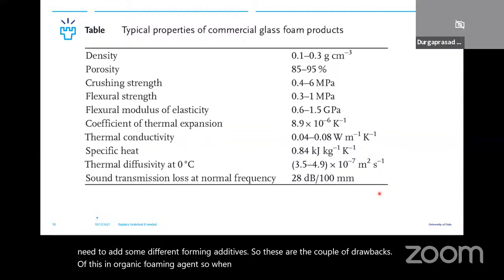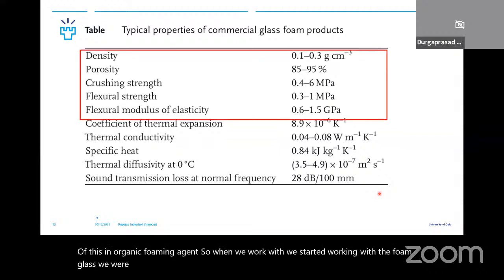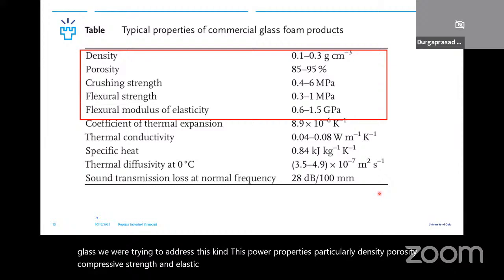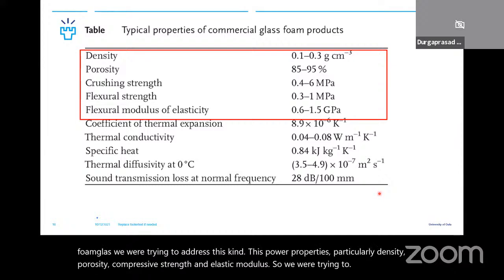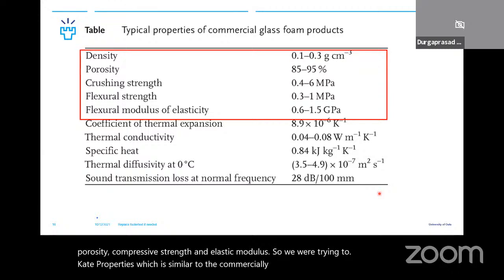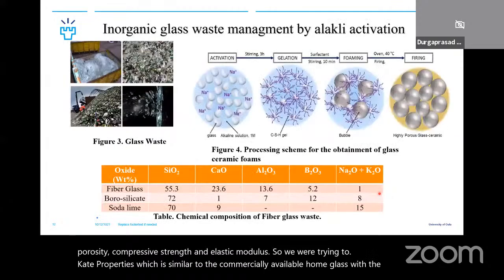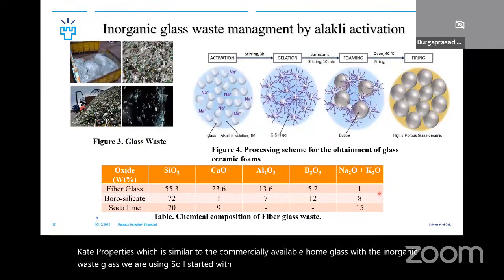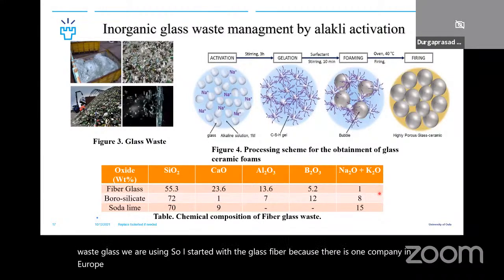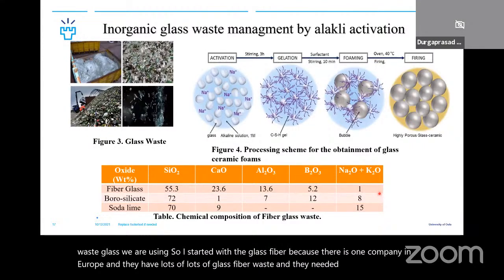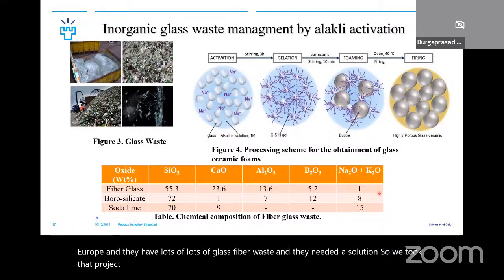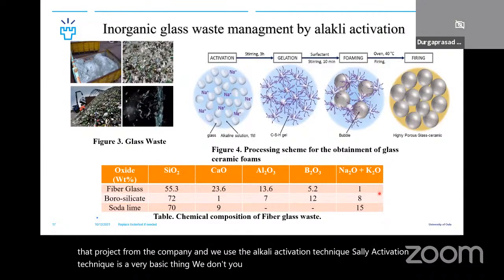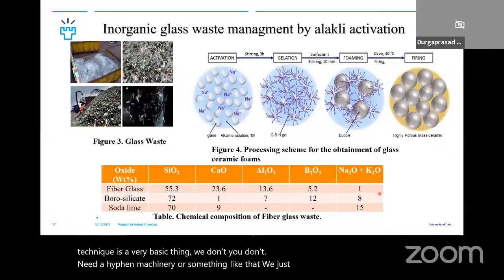So when we started working with foam glass, we were trying to address these properties, particularly density, porosity, compressive strength, and elastic modulus. We were trying to get properties similar to the commercially available foam glass with the inorganic waste glass we are using. So I started with glass fiber, because there is one company in Europe that has lots of glass fiber waste, and they needed a solution. So we took that project from the company, and we used the alkali activation technique. Alkali activation is a very basic thing. You don't need hi-fi machinery. We just started with a simple mechanical stirrer.